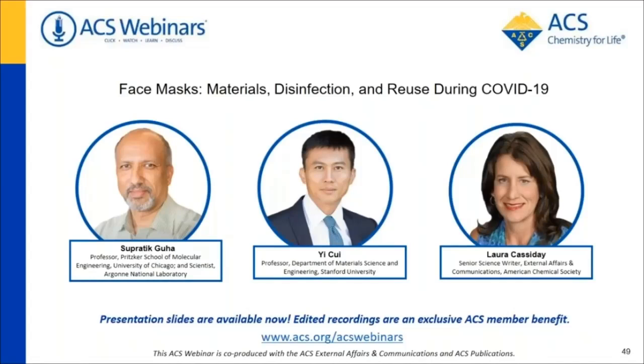But let me also mention that for surgical masks without static charge, the filtration efficiency tends to be on the low side, 30% or so. Some surgical masks' filtration efficiency can go up to about the 60%, 70% range, even 80%, with the static charge. There's a big difference.